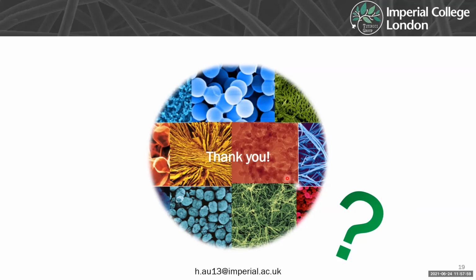Okay, that's a good question. I kind of glossed over that, to be honest. So there is some capacity from the fiber, but this is something I'm still trying to understand, because there's a certain degree, I would describe it, of protection of the fiber by the sulfur deposits. If you just test the fiber itself, because it has such a large surface area, you have a lot of degradation of certain electrolyte species on the fiber. But first of all, I think those happen at a much lower voltage. We're cycling between 2.8 and 1.8 volts, and I think those degradation reactions happen below around 1.5 volts. And I think there's also the element that you're coating the fiber with this protecting layer of sulfur. And because we're charging at a relatively high current density relative to the carbon capacity rather than relative to the sulfur, we don't really see that much effect from the carbon.